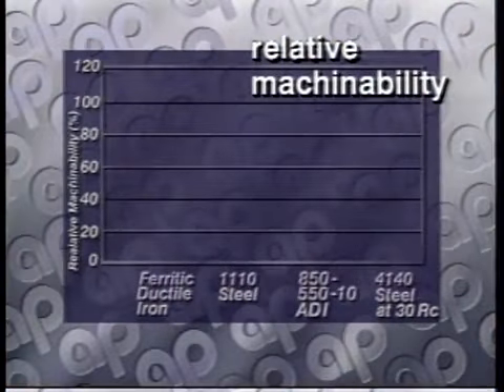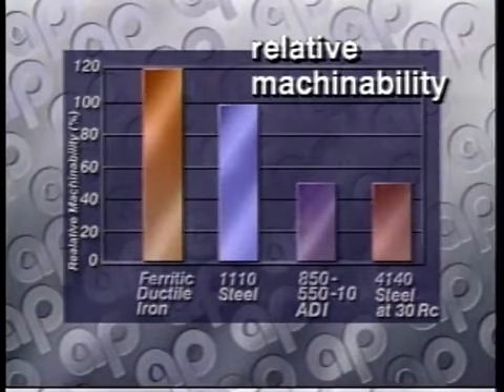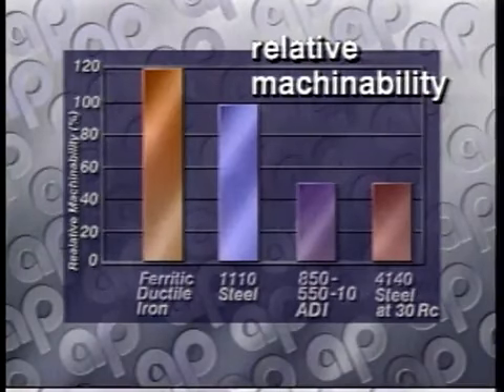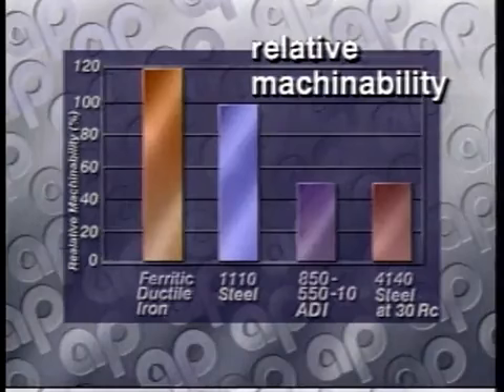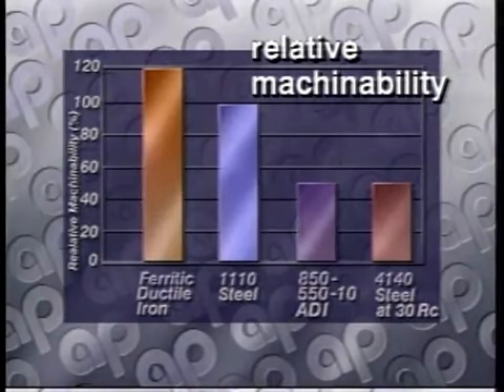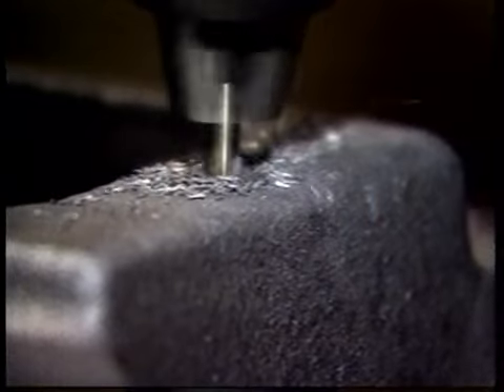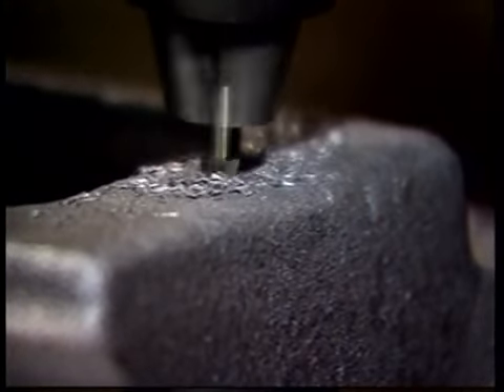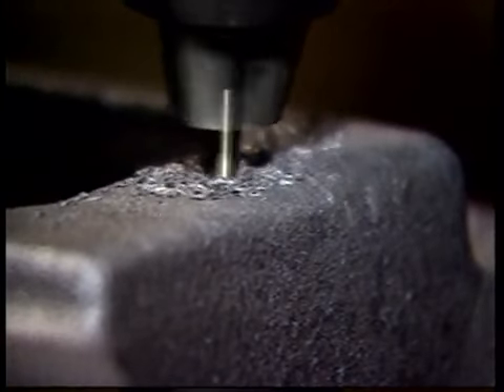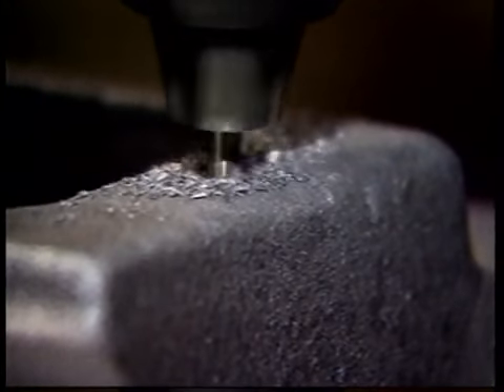Ferritic ductile iron has better machinability than even free machining steel, creating significant savings in the machining process. By machining components in the ferritic condition and Austempering after machining, machine feeds and speeds are increased and tool lives are greatly extended. In addition, machining of ductile iron produces a small discontinuous chip that can be easily stored and recycled.